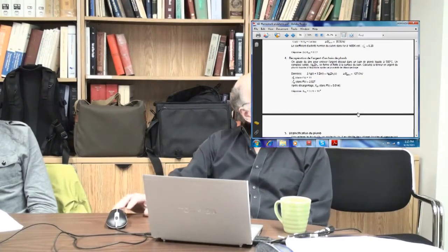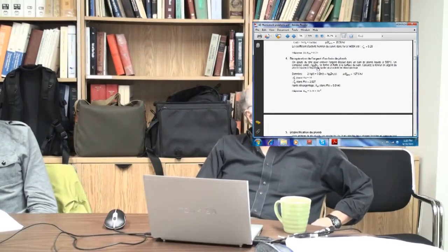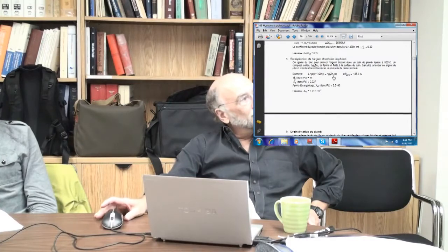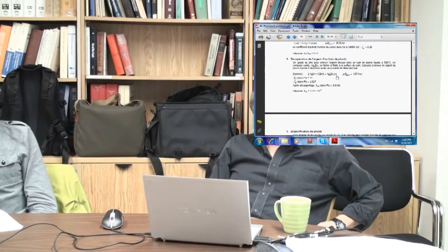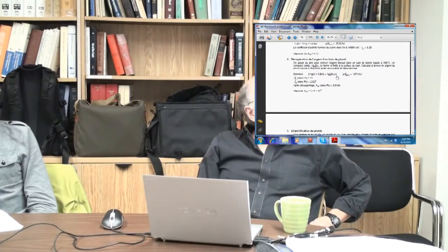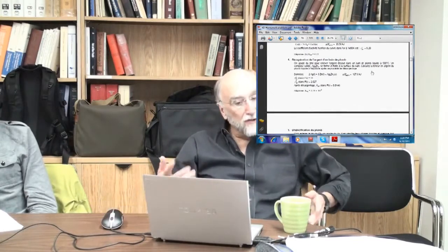Anyway, getting silver out of lead is the same problem. However, there is a trick they use. This is just by chance. There is a solid intermetallic compound called Ag2Zn3, which has a good strong Gibbs energy of formation. If you add zinc to your lead bath, you will form this Ag2Zn3 intermetallic, and it'll float to the surface and you'll get rid of most of your silver that way. Okay. And you have the equilibrium constants here, and you've got the Gibbs energy. So what is the silver content after this process has been completed? Okay.